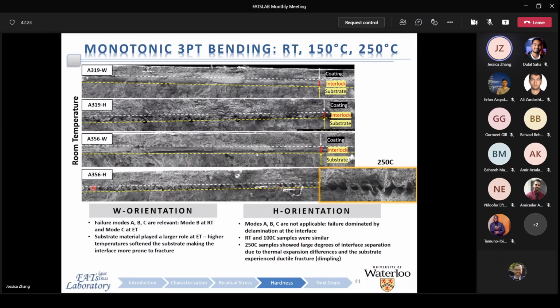And we can actually see that. So this is the A356H. At room temperature, the scale is a little different, but there's a little bit of separation. But at 250 degrees, it becomes quite prominent here for the A356H.